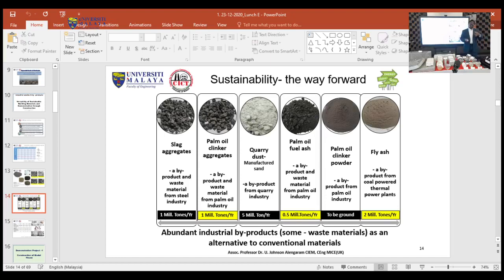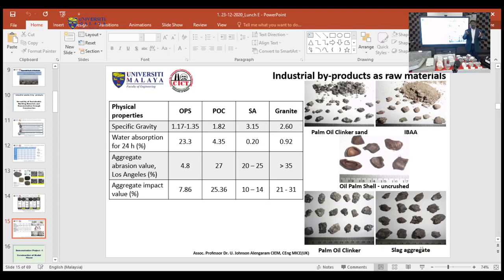And also the aggregates, when it comes to the fine or coarse aggregate, the properties are very important. If you look at the properties, for instance, the palm oil shell that we see here is not like conventional aggregate. It's quite different compared to this kind of slag aggregates. We see here the slag aggregate. It has got a rough surface, which is very useful for the bonding property with the matrix.